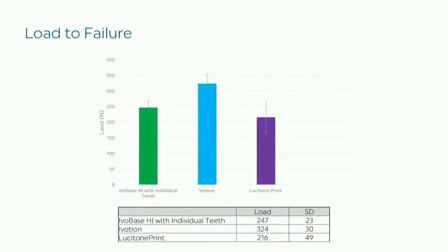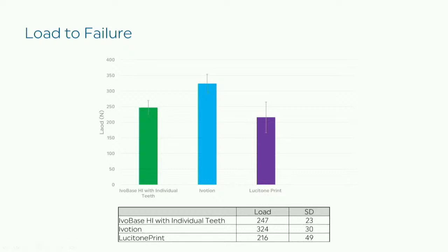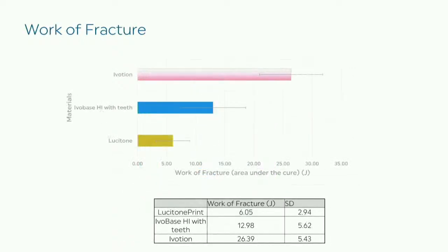And so what we found when we looked down the load here, that the Ivo base with the individual tooth was about 247, and that's consistent with what we're finding in a conventionally processed denture across the board. The Ivotion monolithic was 324, and of course the Lucitone print I thought was going to be higher because I thought it was going to flex more, but it did not. Now the one thing I'll caveat with the Lucitone print material is we did not have it at 98.6, and with their advertised BAM technology within that bioactive material, there may be something to why this fractured lower because it wasn't warm. So the next level of our testing is now heating that material to body temperature to see what kind of result we can get. But Ivotion monolithic definitely stood out in the testing.